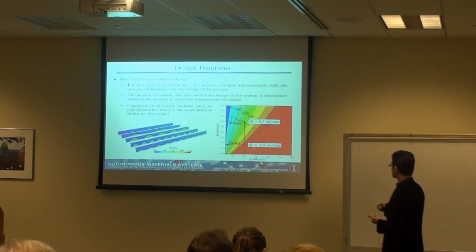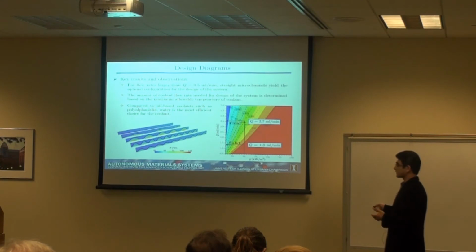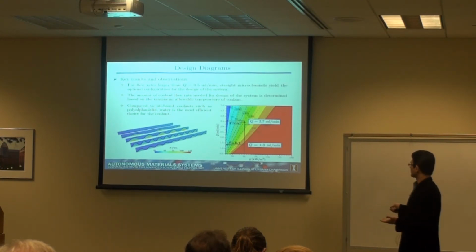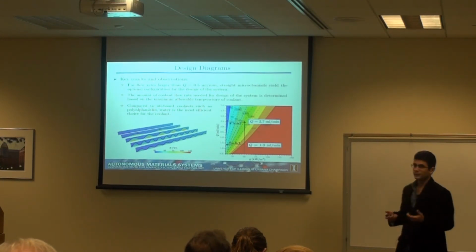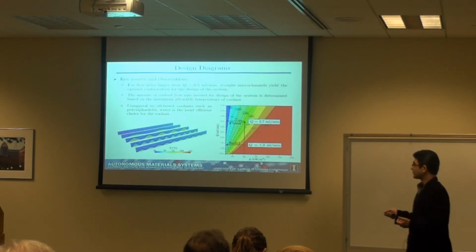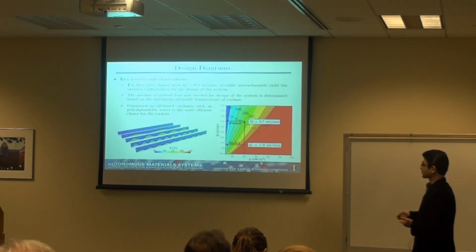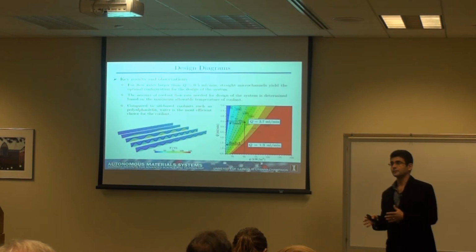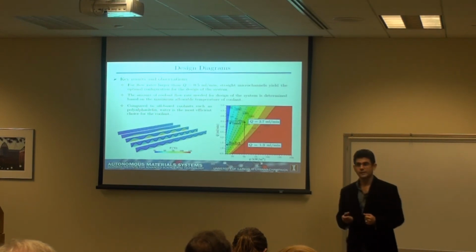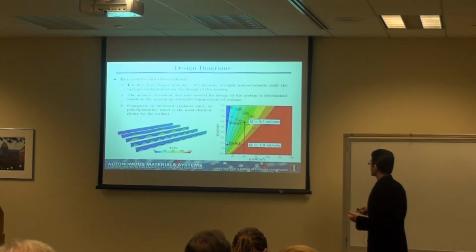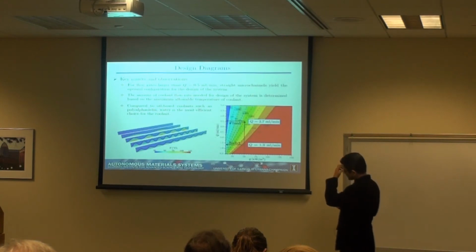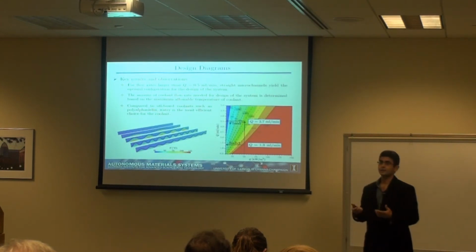case. So for example, this shows that for the solid part, which is the composite, we need to provide a flow rate of 1.3 millimeter per minute, which is not that high. But then you actually have to multiply it almost by 3 times to satisfy the constraints on the maximum temperature of the fluid. So again, the other conclusion was that maybe we have to look at other types of coolant.